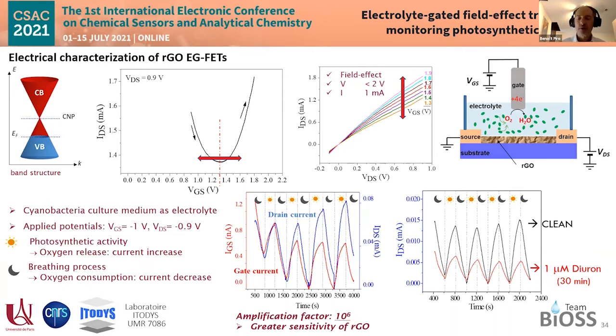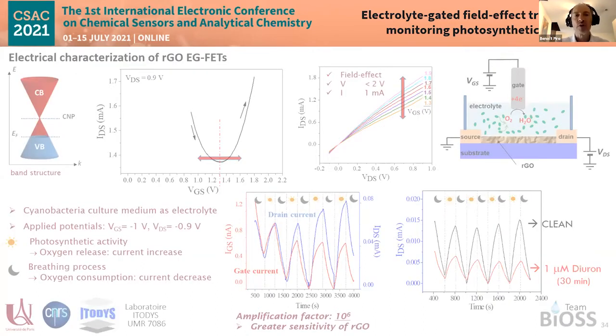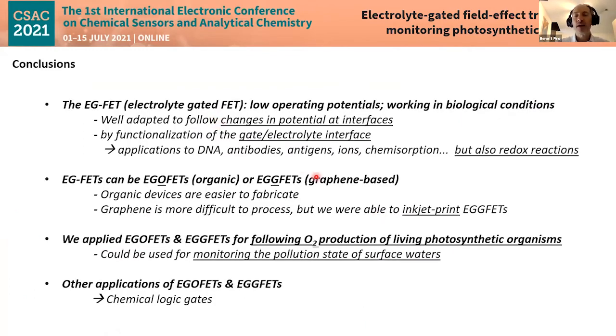So, in conclusion, I wanted to show you that electrolyte gated field effect transistors, which have low operating potentials, work in biological conditions and can be used to detect change at the semiconductor electrolyte interface, but also at the gate electrolyte interface. And, more surprisingly, they are able to follow redox reactions at the gate. That way, we were able to follow the oxygen production and then reduction, electroreduction at the gate, oxygen production by photosynthetic organisms, immobilized on the gate or directly present in the electrolyte medium.